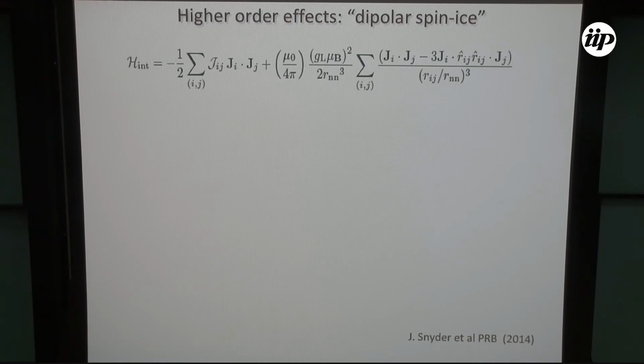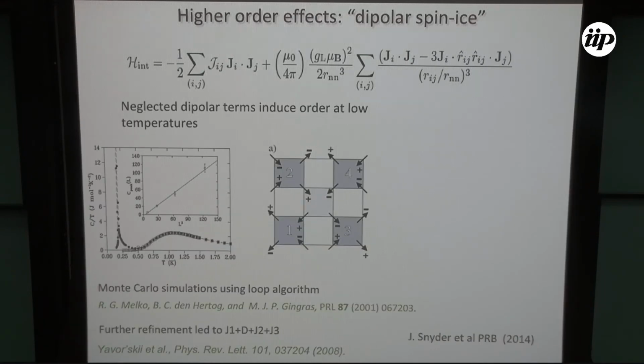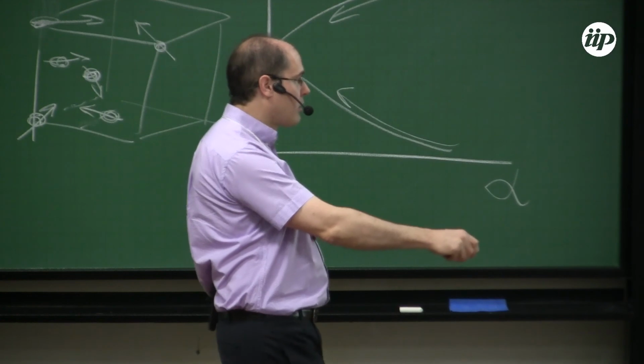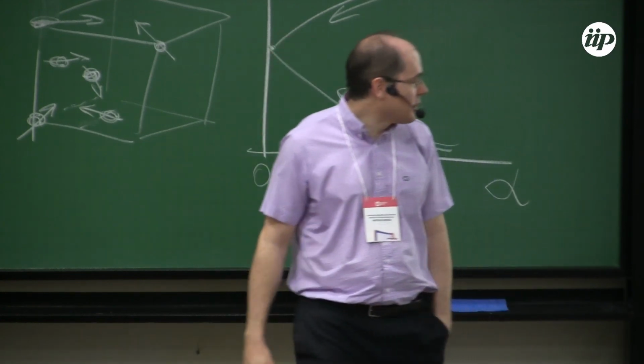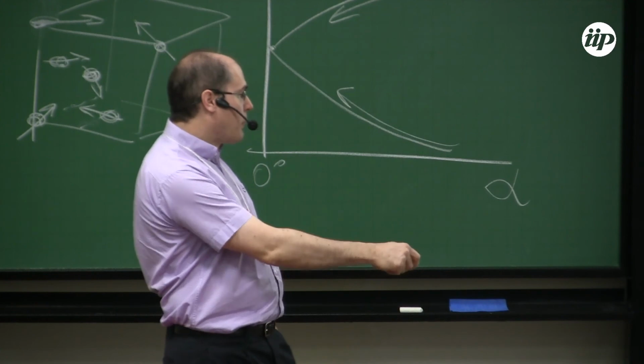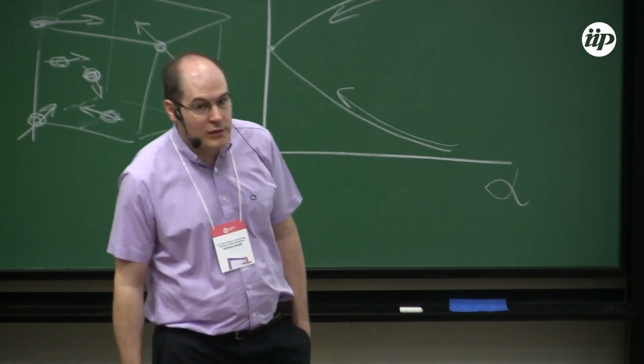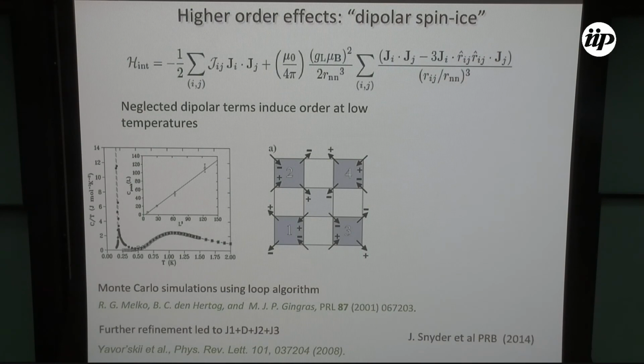And what happens is that this dipolar interaction should, in principle, order the system at very low temperatures. So in theory, there's no real spin ice material if they have dipolar interactions. This is work done by Melko and collaborators, in the work of Michel Gingras in Waterloo. As early as 2001, they predicted that once you take into account that these have really large magnetic moments, so you have a dipolar interaction, the system should order. If you use the parameters for dysprosium titanate, you should see this.